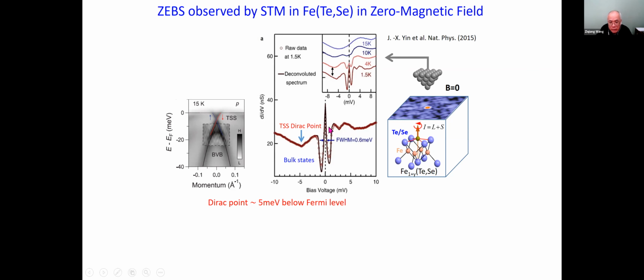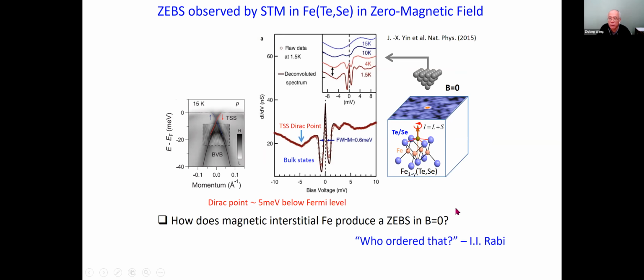So this is indeed what's seen here, a superconducting topological surface state. But how would we have a zero bias peak or zero energy bound state in zero magnetic field? And in fact, this reminds us of the famous quote by Rabi when the muon was discovered instead of the anticipated mesons: who ordered that? And in particular, is this really a bona fide Majorana zero mode?